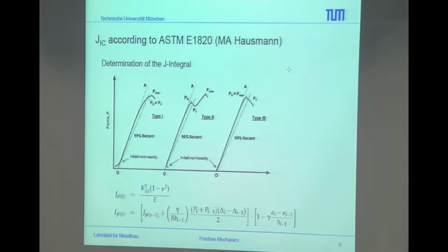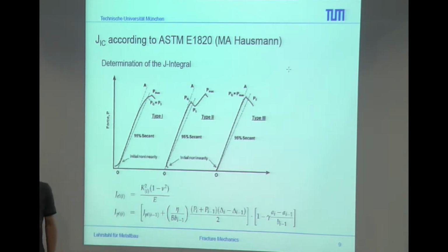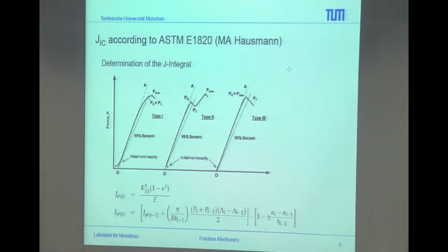linear curve. This would be something like the modulus of elasticity in a tension test, and at the end you use this curve, take the 95% secant, and you get some information about your point PQ, and this point PQ has to be evaluated if there is some inclination.